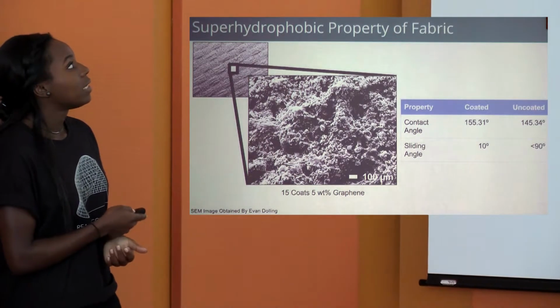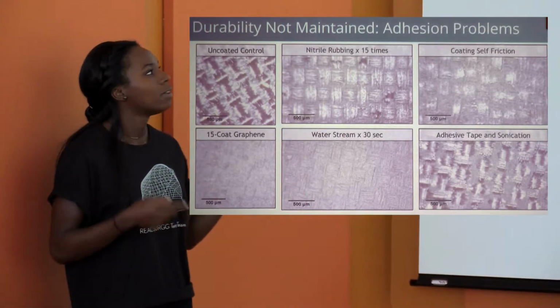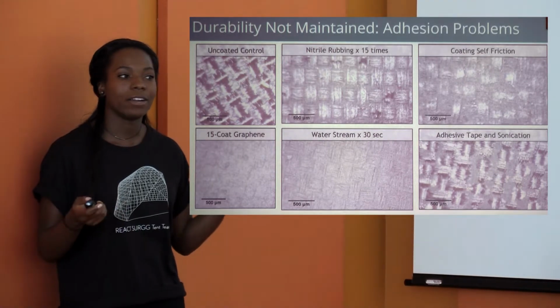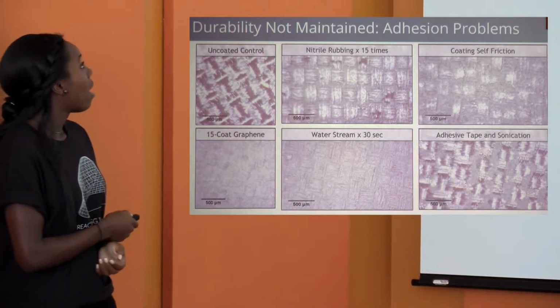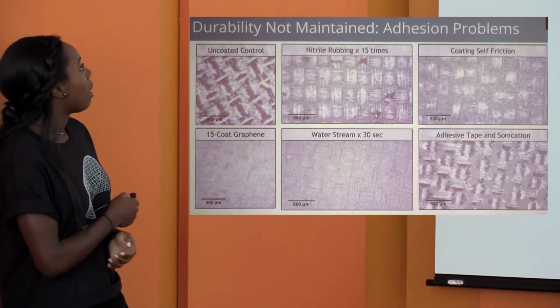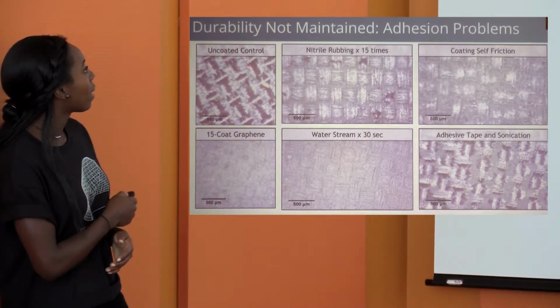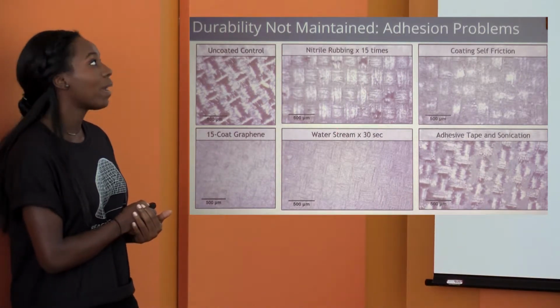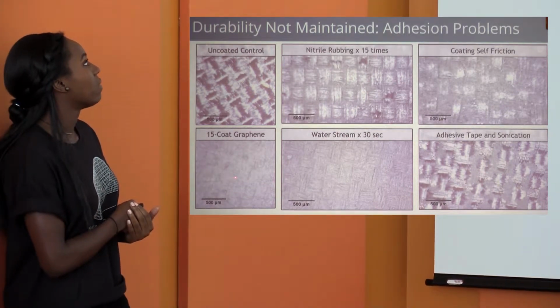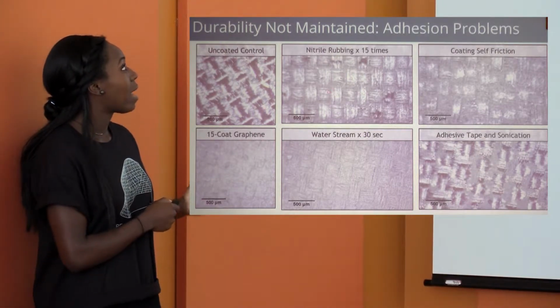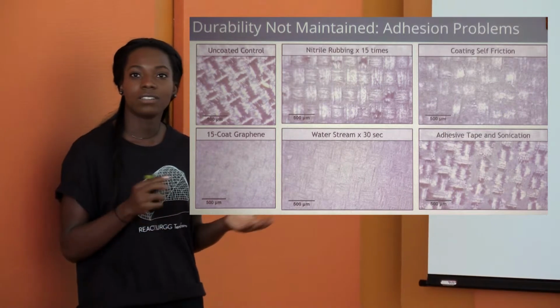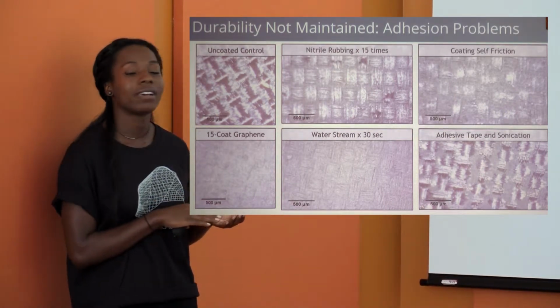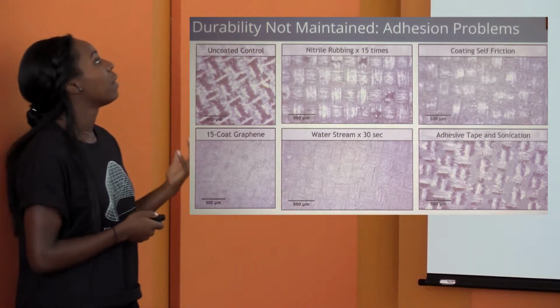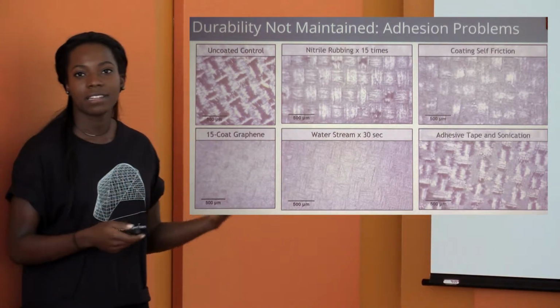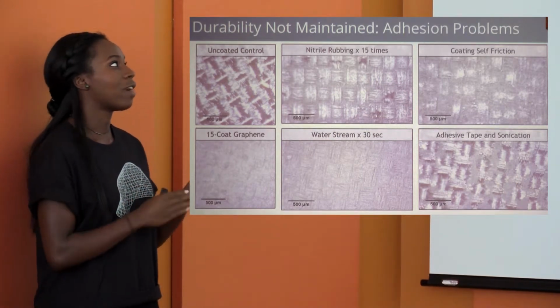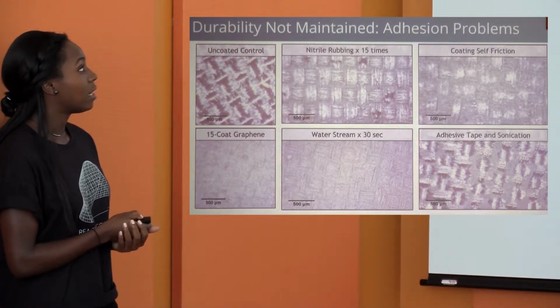And so we ran a series of tests to mimic possible scenarios that the tent might encounter in real life. With these two images, you see an image of just the uncoated fabric, and these are all microscopic images, by the way. And this is just the 15 coats of graphene. The first test we ran was rubbing a nitrile glove onto the coated fabric 15 times. This was to mimic someone assembling the tent, with bare hand interaction with the actual coating.